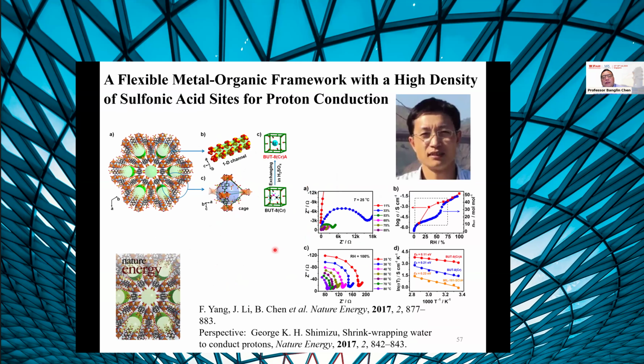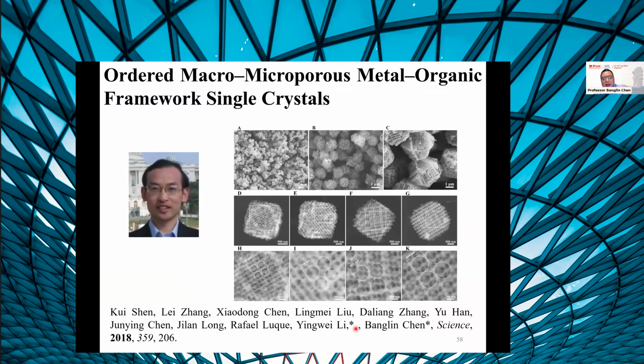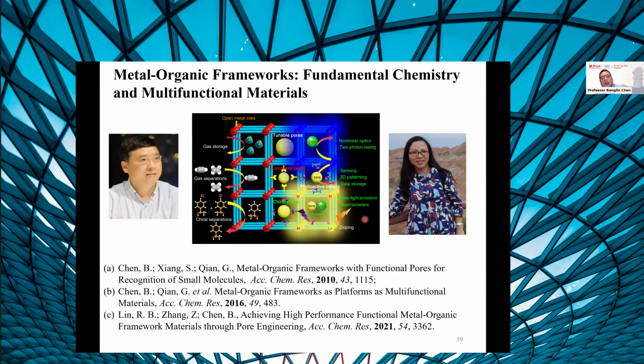And with Yang, we work together on a very high proton conducting material, even under high humidity conditions. And with Yingwei is a micro metal organic single crystal, because this large pore space of about 500 nanometer will facilitate the diffusion, because the micropore will limit the diffusion. So with this hierarchical pores will be quite useful for their industrial application.